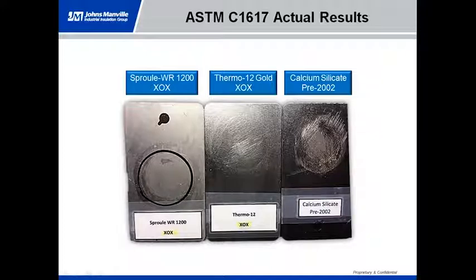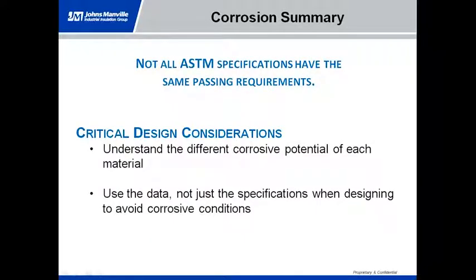So just to give you an idea, here are some actual metal coupons. And if you look at the left two, for either the Sproule or the Thermo 12 Gold, which have the XOX inhibitor, you can see that there's very little degradation to the face. No pitting, no gouging. It looks almost like new metal. If you look at the calcium silicate pre-2002, you can see there's a lot more activity or degradation that was done when they tried to clean that off. So there's a lot more corrosion going on there than there was with the other products with the corrosion inhibitor.